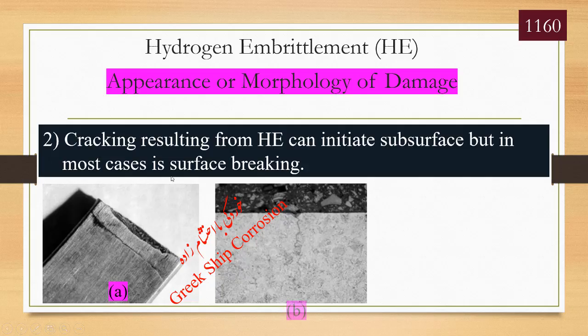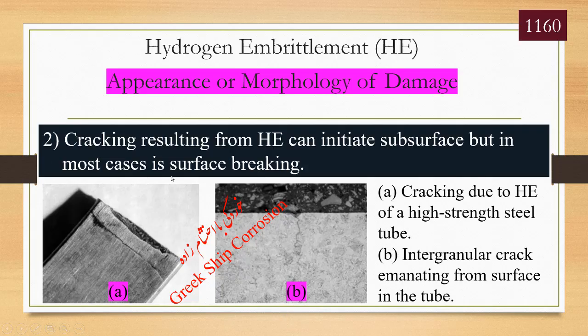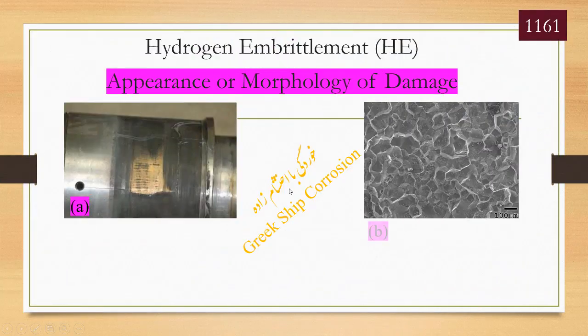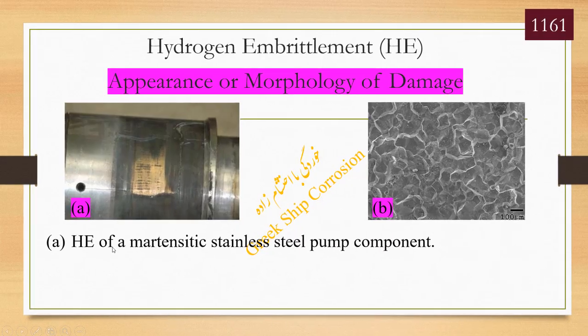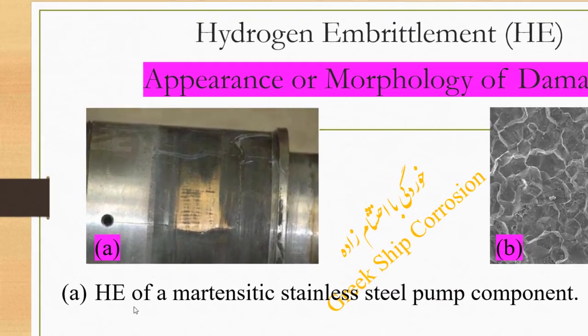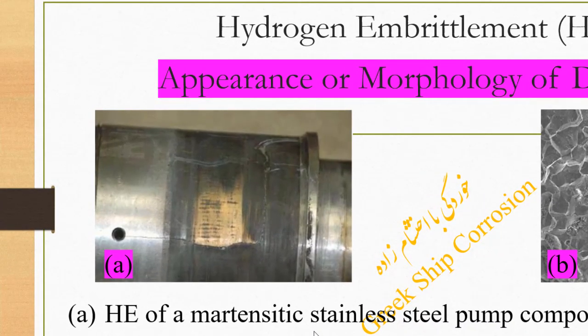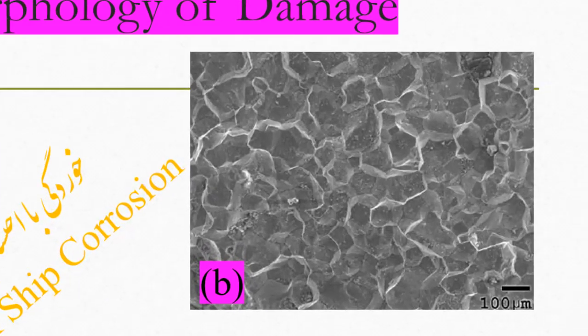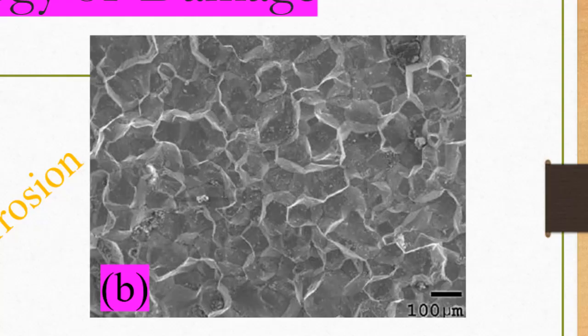A. Cracking due to hydrogen embrittlement of a high-strength steel tube. B. Intergranular crack emanating from surface in the tube. And in these figures, A shows hydrogen embrittlement of a martensitic stainless steel pump component, and B shows high magnification fractograph of the fracture surface showing intergranular nature of the cracking.